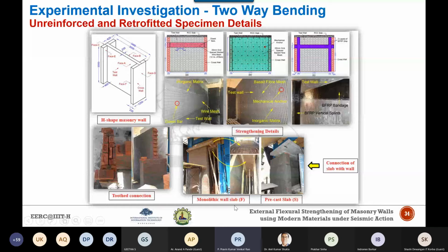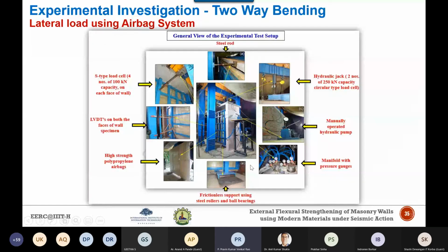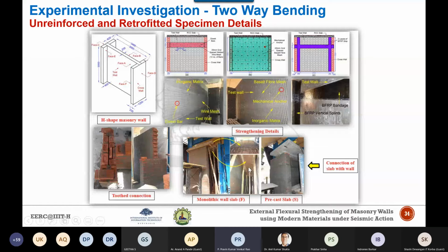Whereas in case of the flexible diaphragm, as I said, the connection between the roof and the wall is simply obtained by using a green mortar layer. So this represents the flexible diaphragm, where my three edges, the two vertical edges and one bottom edge, are under fixed conditions, whereas the top edge is non-restrained. Now the question arises: how to apply realistic seismic forces in the out-of-plane direction in order to fail this particular wall in out-of-plane bending?